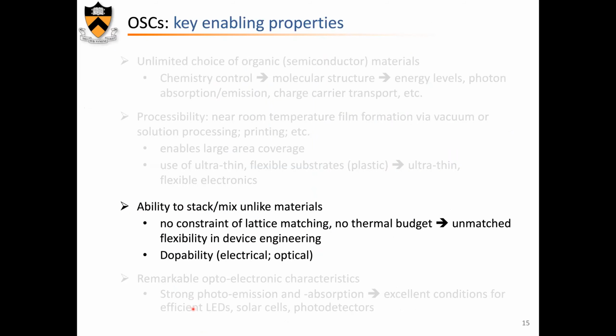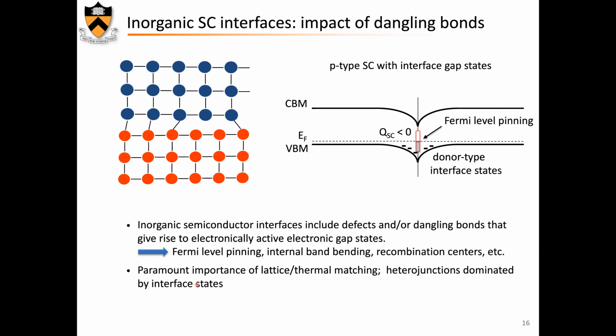The ability to stack and mix. Let me explain. Here you have a conceptual interface between two inorganic semiconductors. And if you want to put gallium arsenide on silicon or whatever, they do not have the same lattice constant. They do not have the same thermal budget when you grow them, and therefore at the interface, you will undoubtedly have defects and dangling bonds, broken bonds, and so on. And these are known to induce electronic states in the band gap of semiconductors. And that leads to what is called Fermi level pinning. These are recombination centers. It's generally pretty bad for electronic devices.